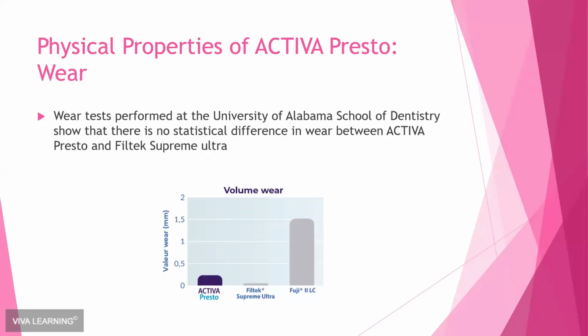And then when we're looking at the wear of this product, the study was done by the University of Alabama School of Dentistry, and it shows that there's no statistical difference in the wear between Activa Presto and Filtek Supreme Ultra. So again, this is a glass ionomer derivative that is responding more like a traditional composite.